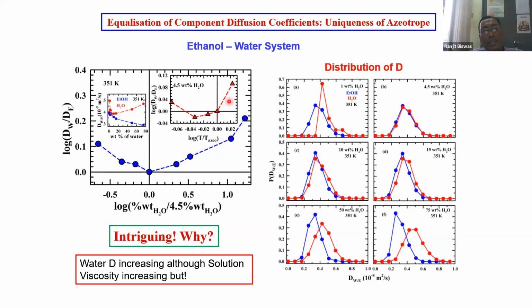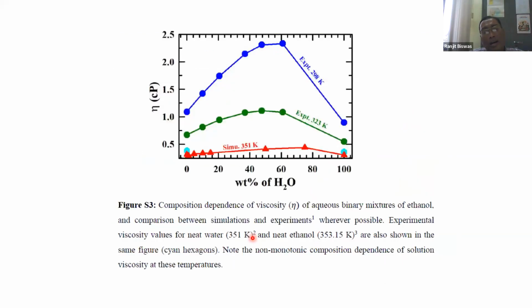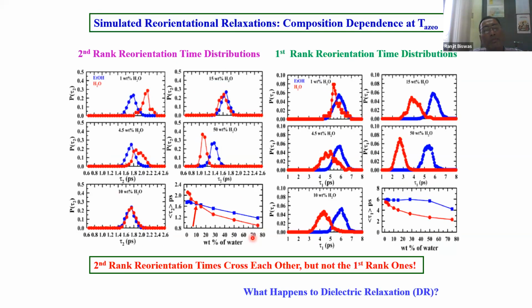And you can see in this plot that we are sitting at the azeotropic composition, changing the temperature. And when the temperature becomes the azeotropic temperature, you see again that equalization of component diffusion coefficients. Very intriguing. I connected this to the viscosity of the medium.